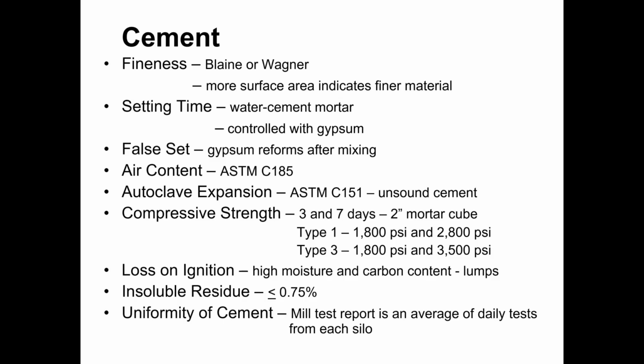Uniformity of cement. This is just an indication of the average daily test from a silo. Generally the mill report the plant is going to receive is going to be a combined average for all of these different test values. The cement mill will do testing on a regular basis while cement is being produced, but that cement is dumped into a silo and blended with other days of production, such that the mill report will have average test data for a given month. And that's usually what the plant will receive, a monthly mill report indicating the average test data for that cement over that month.